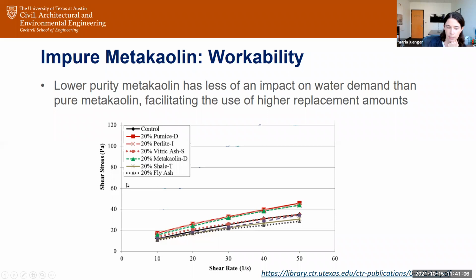So in this particular example, these are rheology plots of shear stress versus shear rate, where the slope gives you some indication of viscosity. The black line is just a Portland cement mixture, and the metakaolin is this green one, which has a slightly higher viscosity, but still within what's reasonable for a concrete mixture, whereas the pure metakaolin, which I don't have on this plot, but we do have data for, is a much, much higher viscosity mixture. Sorry, lower viscosity, higher. I always get mixed up with that. I have to think about syrup.